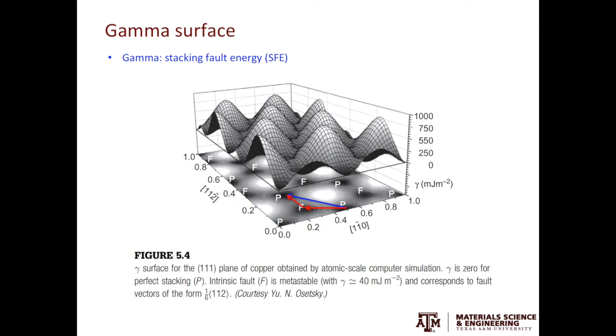Now, let's look at these saddle points. These saddle points correspond to a local energy minimum. Note, they are not at the global energy minimum. They correspond to the partial dislocations. Last are these valleys, where the energy is at the global minimum, and they correspond to the full dislocations. When we glide atomic planes on top of each other, ideally we want to go from one global minimum to another global minimum, as shown by this blue arrow here. But to go directly along the blue arrow, you have to climb an energy hill, which is not favored. Instead, if you follow the red arrows, you are always going downhill. You have two partial dislocations, you can also end up in the energy minimum. By looking at both the strain energy of dislocations and looking at the gamma surface, we learned it is favorable to have two partials over one full dislocation.